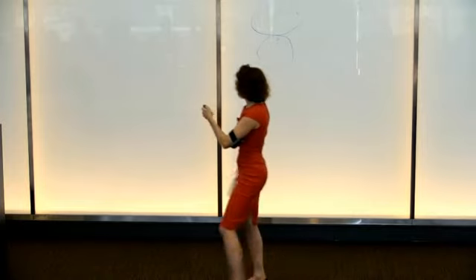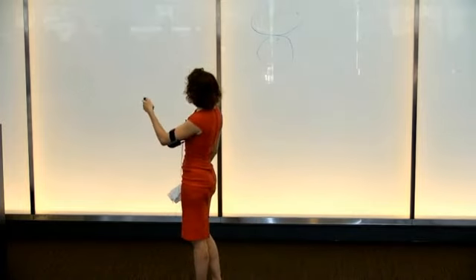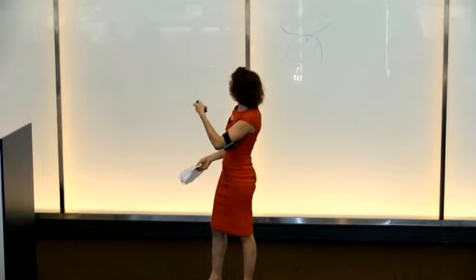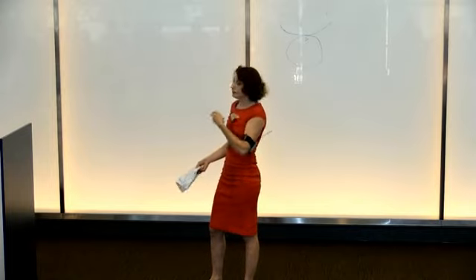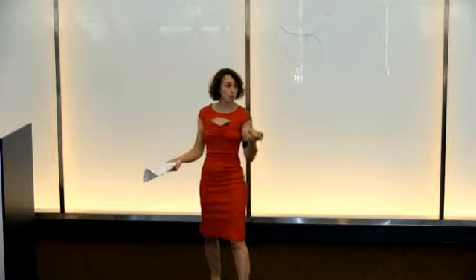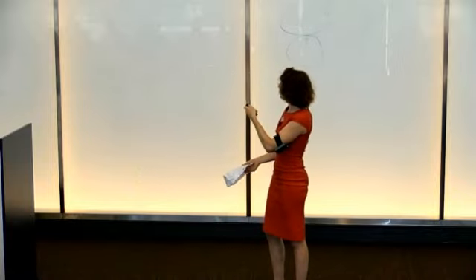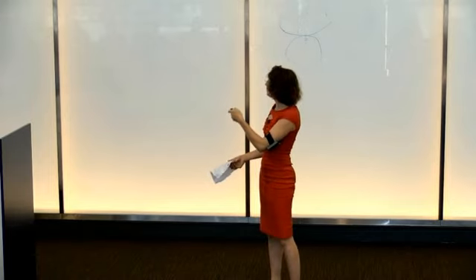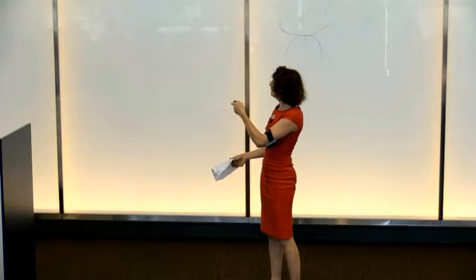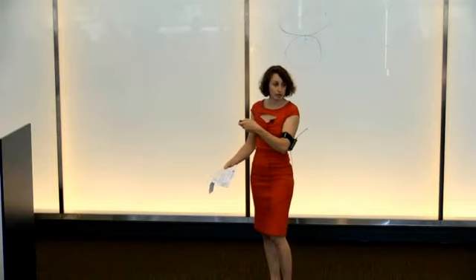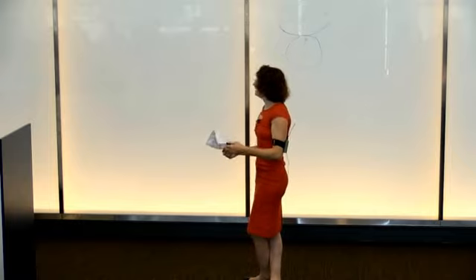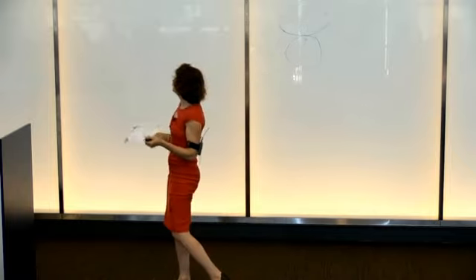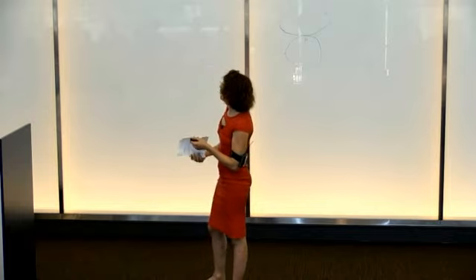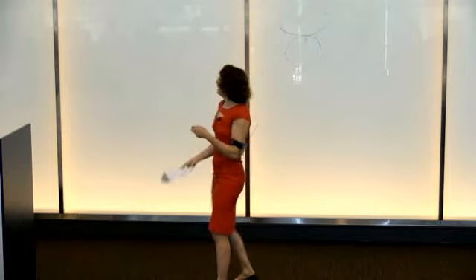And this is what I plot here. So the y-axis is the average height once the sheet is relaxed, and the x-axis is the height of the middle forced point. If there was no hysteresis, if there was no memory in the system, going up and going down would follow the same curve. But in this case, since there is memory, I'm going up along one curve, and I'm going down along a different curve. Which means that the shape remembers the previous configuration.